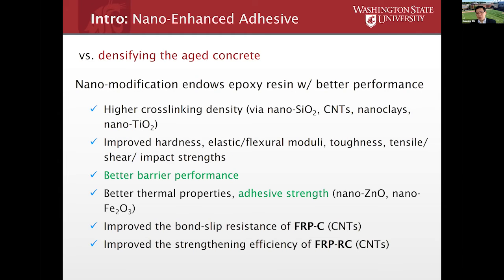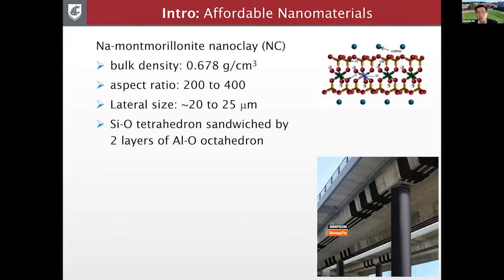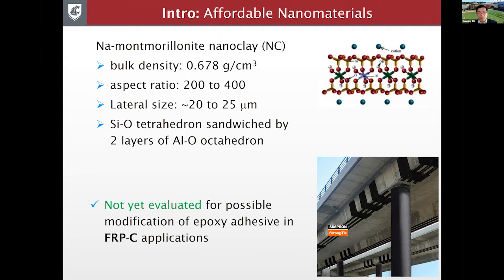And also, when it comes to FRP concrete composite materials, so far the studies I've seen, at least in the published domain, are only on carbon nanotubes. And as you know, these materials are very expensive. So how about more affordable nanomaterials? So we go back to the sodium montmorillonite nanoclay, a 2D material with a lateral size of about 20 to 25 microns, but a thickness of a few nanometers. And this material hasn't been evaluated for possible modification of the epoxy adhesive in FRP concrete applications.